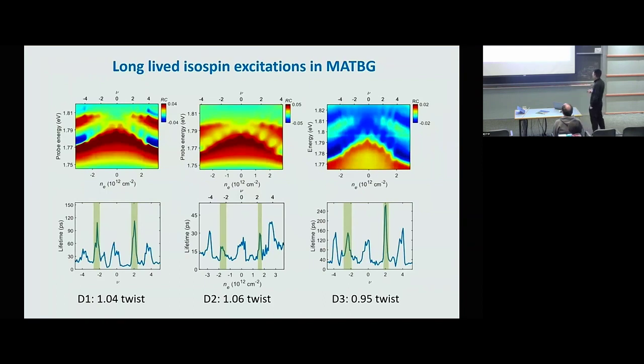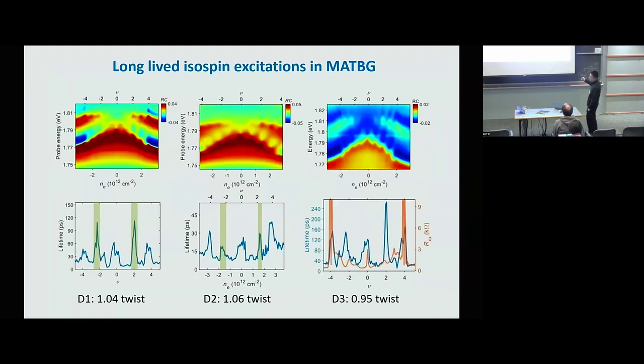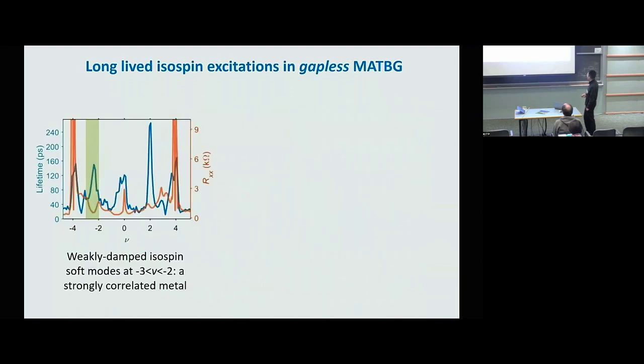And we also have a device, the third device, which can directly allow us to compare transport and dynamics. And in transport, it's not that surprising. It's quite common. So we see a strong peak at 4 and some weaker peaks at the integer fillings 1, 2, 3. Our temperature is pretty high, it's 2.5 Kelvin. So these peaks are not that impressive, but they're there. And we can directly see that on the hole side, this slow dynamics is actually between -2 and -3. It's well away from the insulating state at -2.